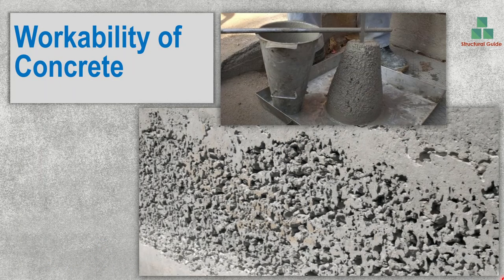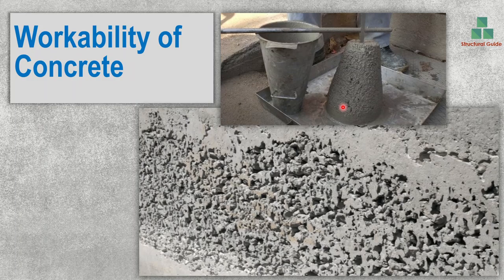How does workability affect the formation of honeycombs? As you can see in the slump test, you can see honeycombs or small cavities formed there. Why is this? Low workability. This could be due to a low water-cement ratio, low water content, or delay in concrete getting to the site — some workability loss could occur due to those kinds of issues.